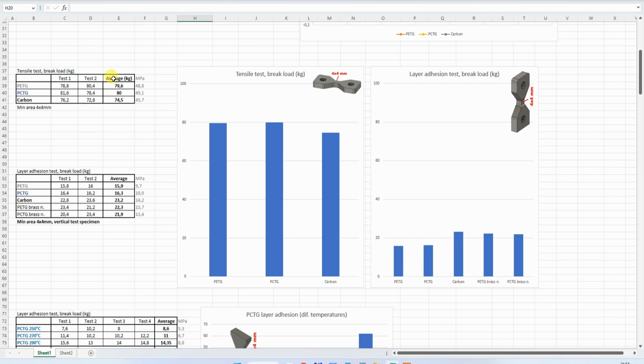The tensile test, everything is okay here. Average values for the PETG version of the filaments. And now the layer adhesion test. So here you can see these 3 numbers are printed with a hardened nozzle, and then I reprinted them with the brass nozzle using basically the same G-code. And here you can see, interesting, the layer adhesion is better, but quite low values. So 20 kilograms, that's quite low.